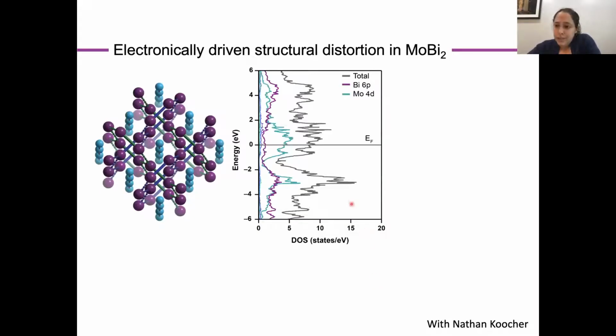Here's this density of states diagram that he generated for the structure, which is in a lot of ways exactly what you would expect at your Fermi energy, separating your occupied from your unoccupied states. You mainly have molybdenum 4d character, although there's also a fair bit of bismuth 6p character in some of the valence states as well. But I was drawn to the fact that at about 1.4 electron volts below the Fermi energy, there is a minimum in the density of states, which is often called a pseudogap and has been implicated in the observance of such structural distortions.